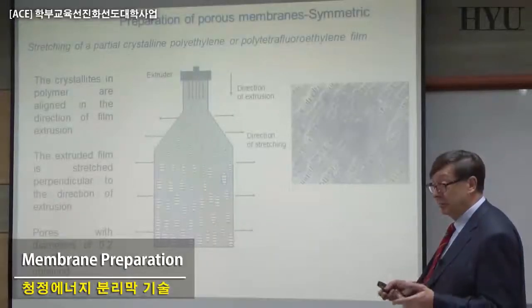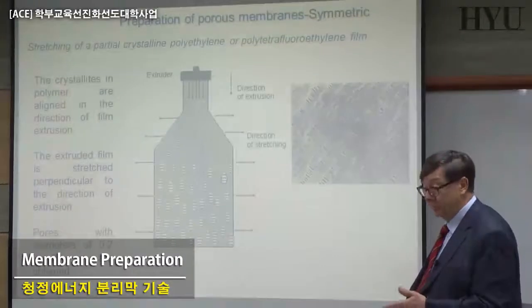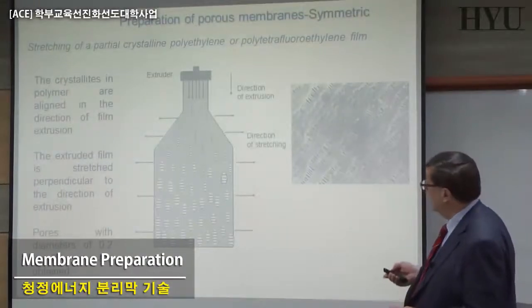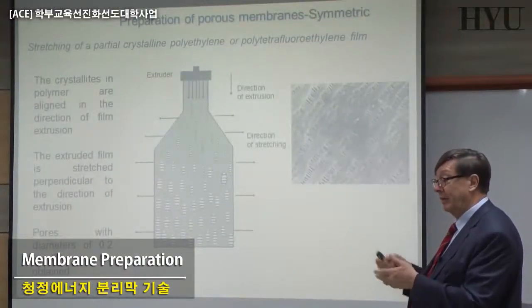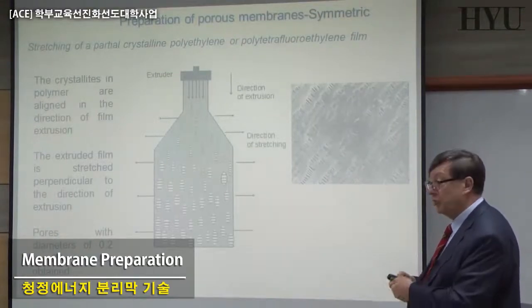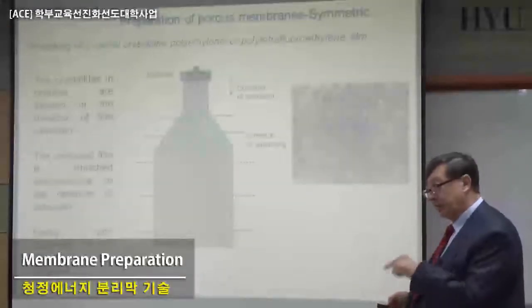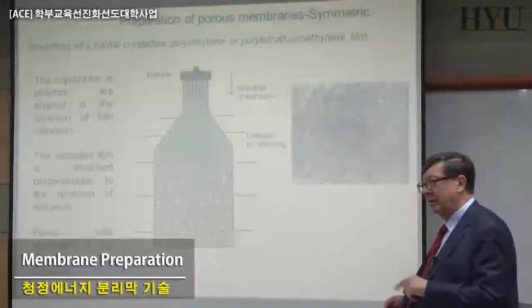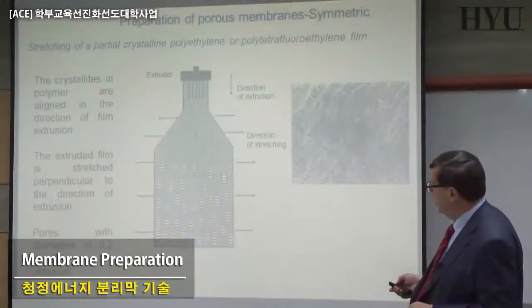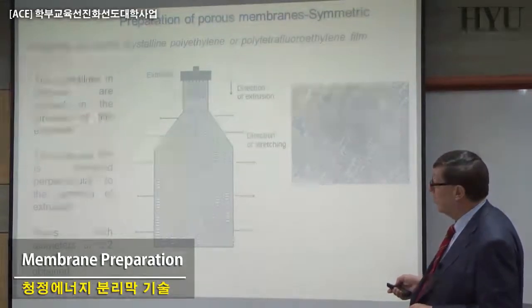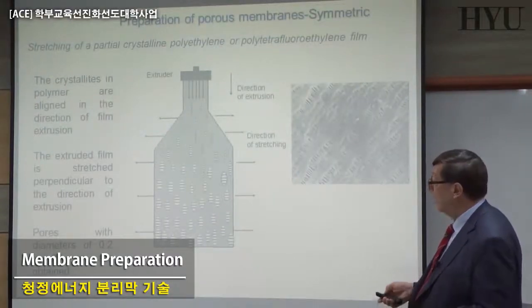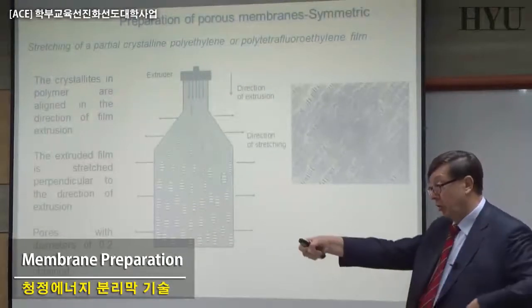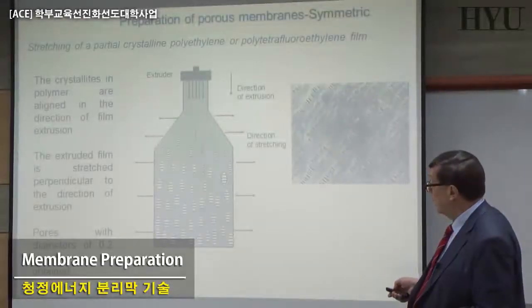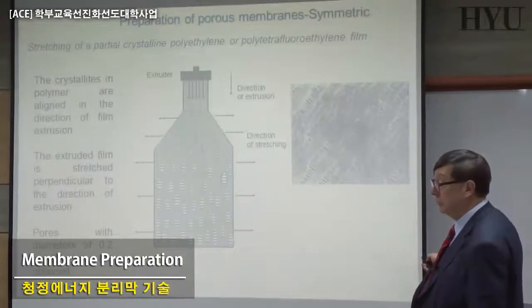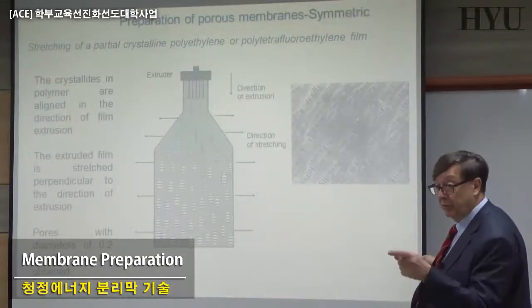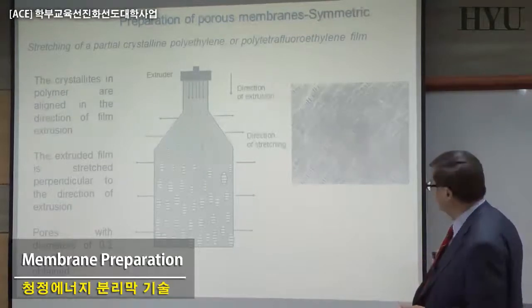Another way of making membranes, largely utilized, and some of you, depending on your shoes, is just to combine the formation of your membranes with stretching. Stretching at a certain specific temperature, normally higher than the Tg, the glass transition, you can induce the formation of pores. You can extrude the film, and during the extrusion, stretching can be perpendicular or longitudinal, in both cases you can have a very nice distribution. This is Gore-Tex. A lot of you are buying Gore-Tex. That is the way of doing it.